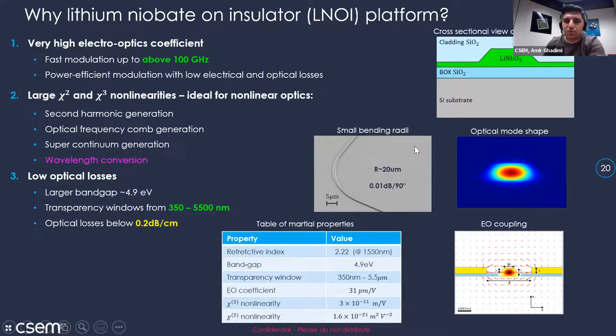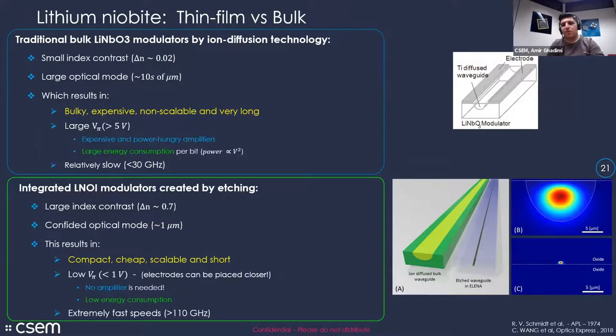So this shows you the cross section of our waveguides. Normally we partially etch. We have the ability to fully etch, but for very good reasons we partially etch. This shows the confinement of the modes. We can do relatively sharp bends with low losses that actually allows us to do very dense integration.